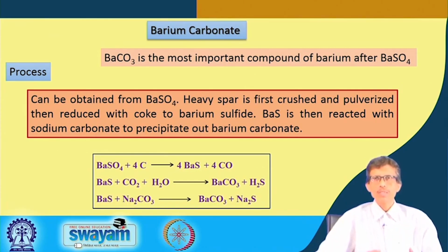One is by utilization of a gas molecule, carbon dioxide. So, you pass the gas in the presence of water, basically you are supplying carbonic acid. So, a mixture of these two can give you the corresponding conversion of sulphide to carbonate, or in the other case you add sodium carbonate, where the process will be costlier, because sodium carbonate you have to identify as a separate material, and it also has some price. But carbon dioxide is a very cheap material and water is also readily available.